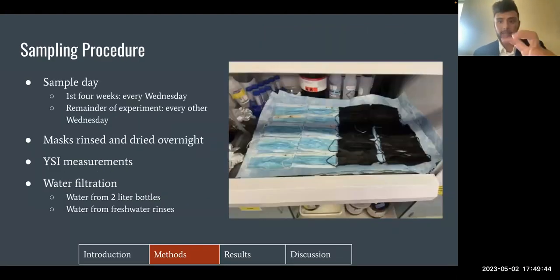During this experiment, sampling took place every week for the first 4 weeks and every other week for the remainder of the experiment. On each sampling day, 1 bottle filled with black and blue masks was removed from the control and experimental groups. Each mask was removed from its respective 2-liter bottle, rinsed in 500 milliliters of fresh water, and dried overnight in a fume hood, which you can see how they looked while they were drying in the picture on the right.